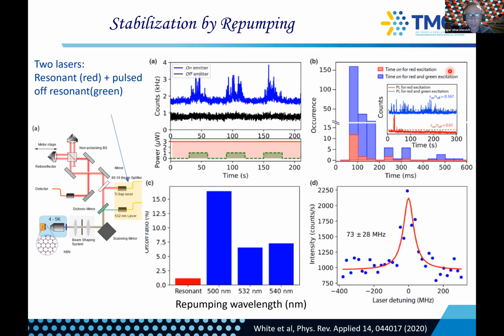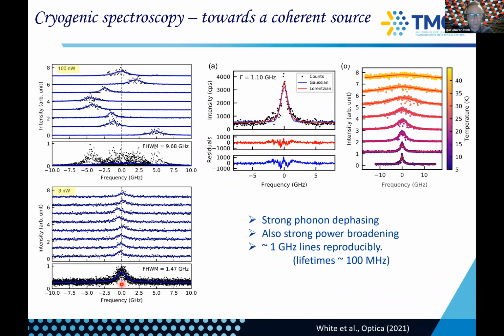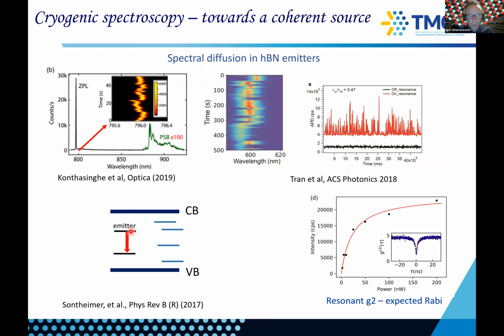So the answer to the first part, actually, this technique is used for quantum dots and color centers quite often. So we stole it from them, as we stole many other things. So it works basically with any system. The reason why 500 nanometer works better than 532 or 480, we also went a little bit down, is actually kind of random. But what it probably tells you is where the other trap is. So if you think about this two-level, let me go back two more slides. If you think about other trap states where the charge can go, what the green laser does is it will reinitialize a charge exactly at your ground state so that when your resonant laser comes, it can promote it. And you need this reinitialization.